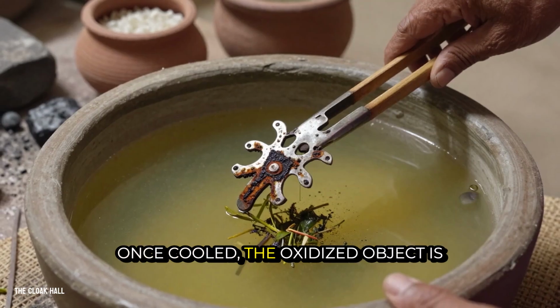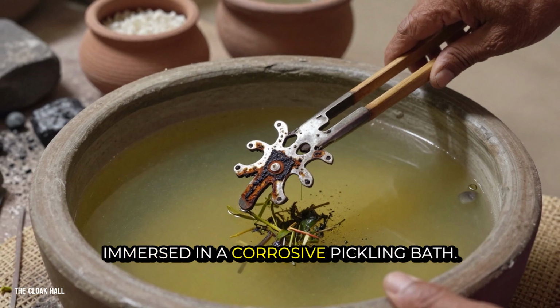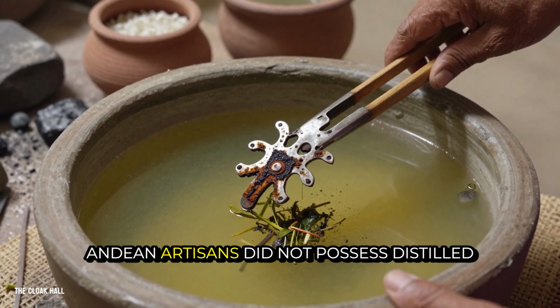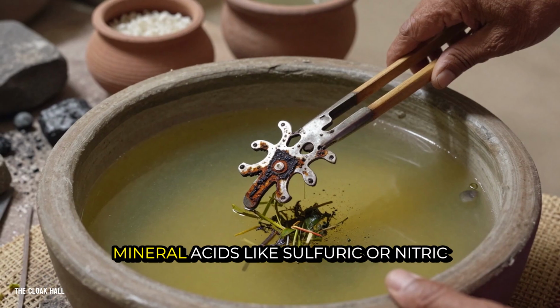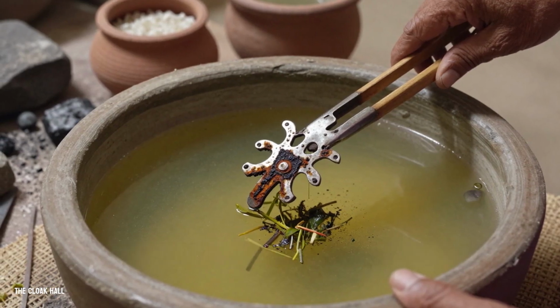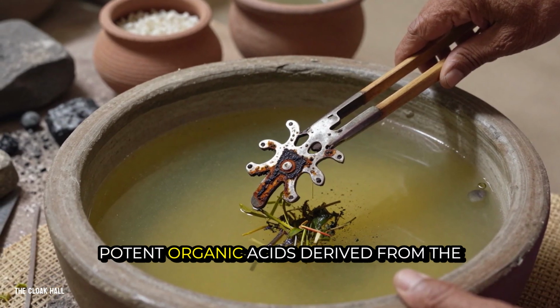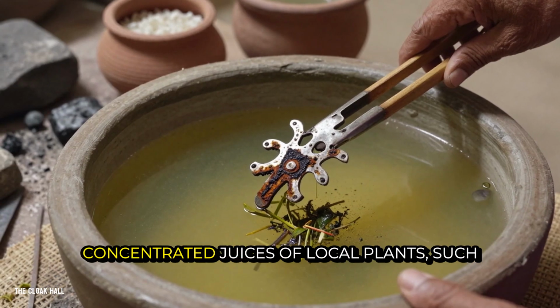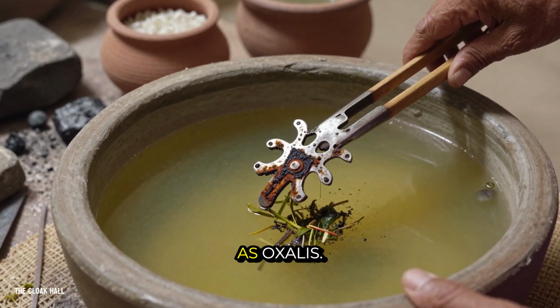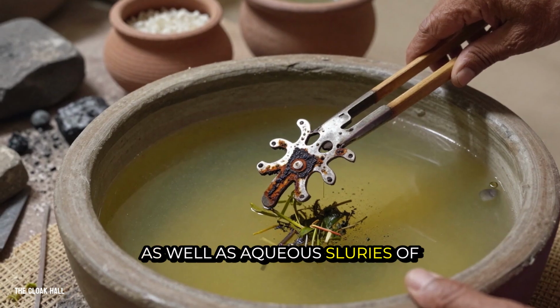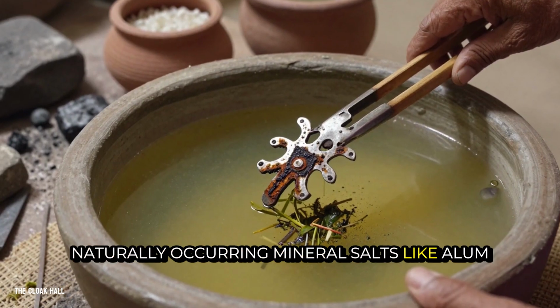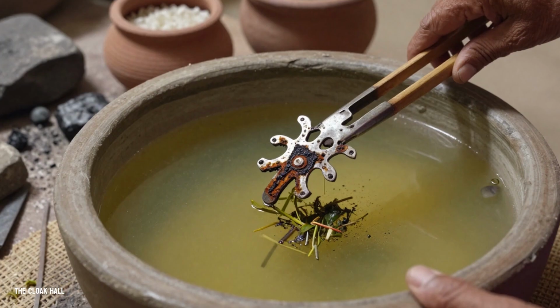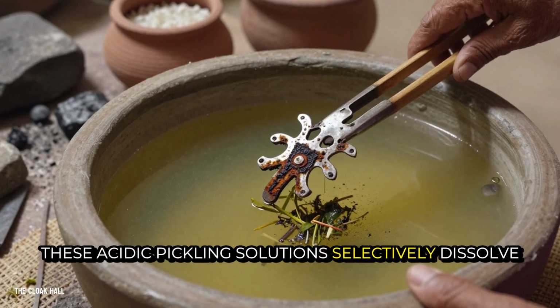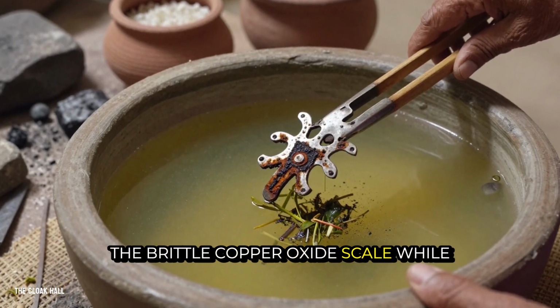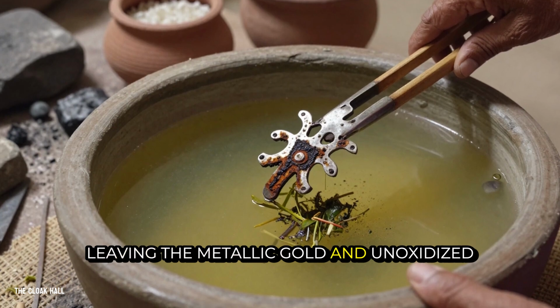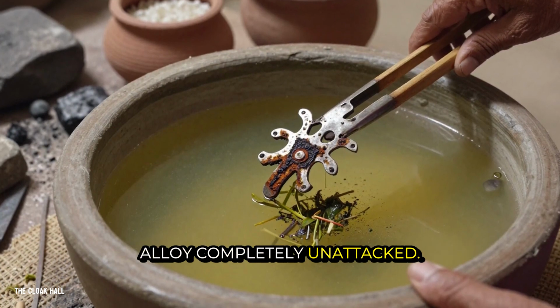Once cooled, the oxidized object is immersed in a corrosive pickling bath. Andean artisans did not possess distilled mineral acids like sulfuric or nitric acid, but they had access to potent organic acids derived from the concentrated juices of local plants, such as oxalis, as well as aqueous slurries of naturally occurring mineral salts like alum and ferric sulfates. These acidic pickling solutions selectively dissolve the brittle copper oxide scale, while leaving the metallic gold and unoxidized alloy completely unattacked.